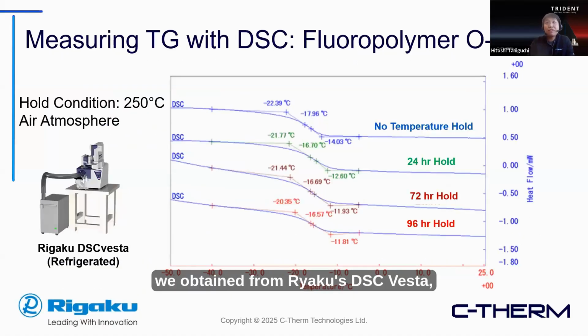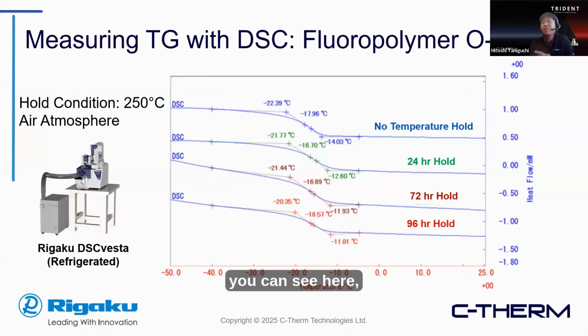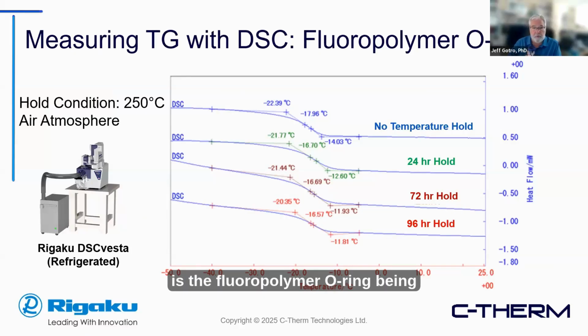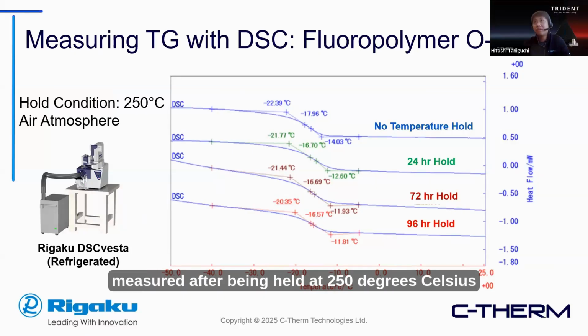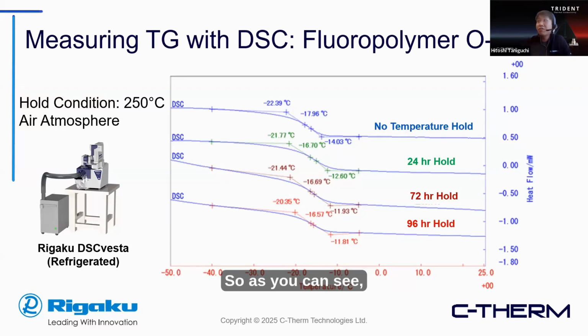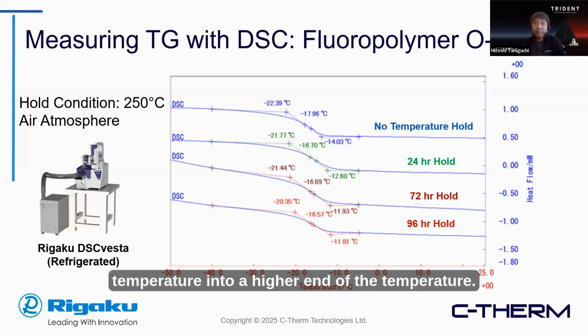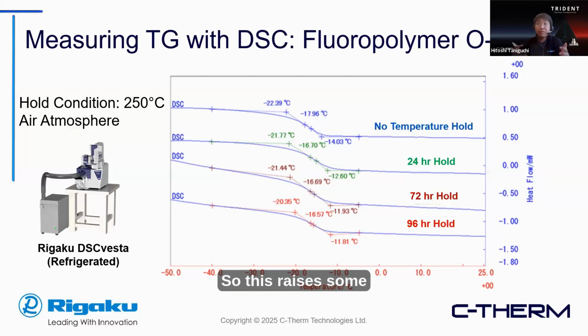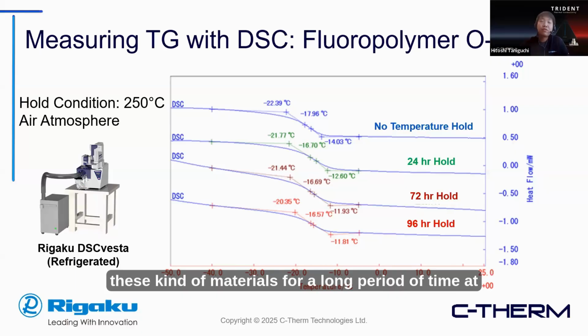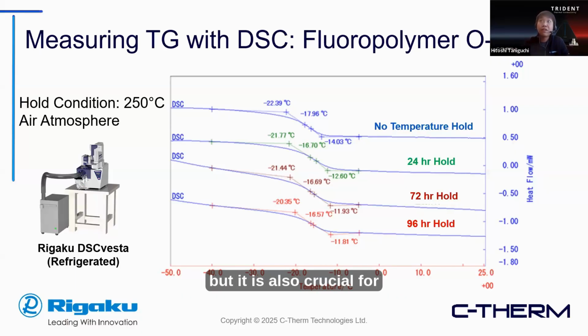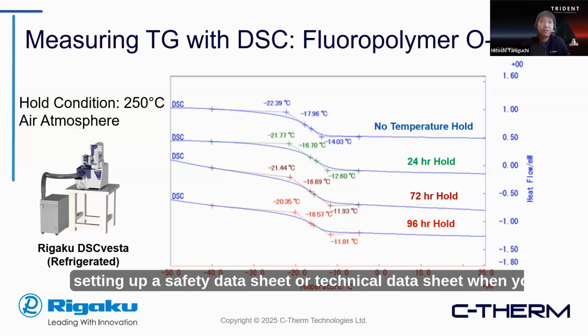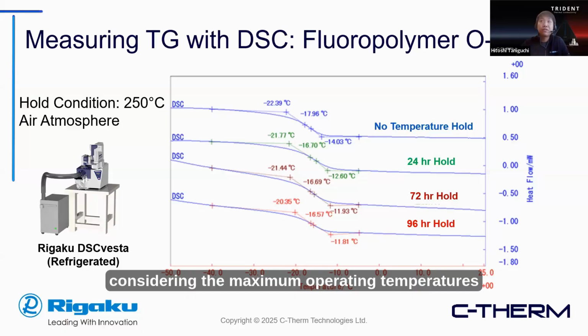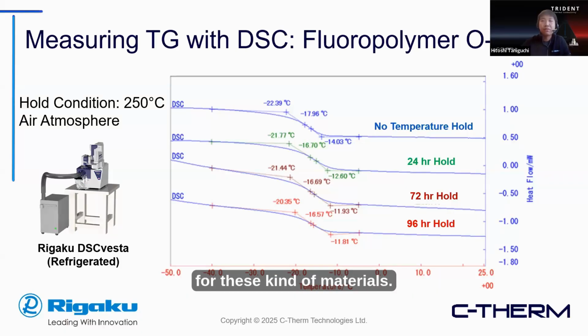An interesting data set we obtained from Rigaku's DSC Vesta, you can see here, is a fluoropolymer O-ring being measured after being held at 250 degrees Celsius for different durations. As you can see, as the hold durations increase, we see a shift in the glass transition temperature to a higher temperature. This raises some safety concerns if you're using these kinds of materials for a long period of time at different temperatures, but it is also crucial for setting up a safety data sheet or technical data sheet when you're considering the maximum operating temperatures for these kinds of materials.